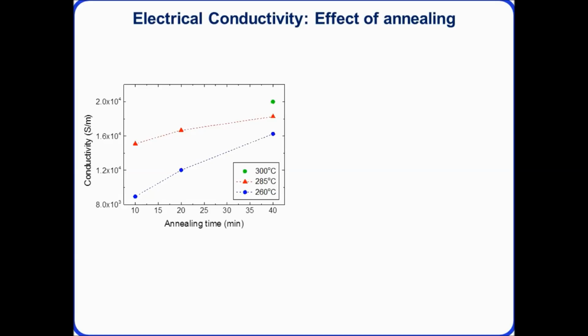But we can also then do further annealing, which is also substrate dependent. So some plastics you cannot heat beyond 100 degrees, but if you're printing on glass or on Kapton, which is another polymer substrate, you can heat these to much higher temperatures beyond 300 degrees. And so again, we can use heating treatments to further improve the conductivity of the printed films.